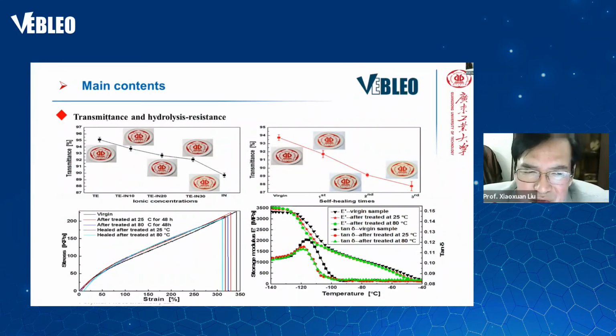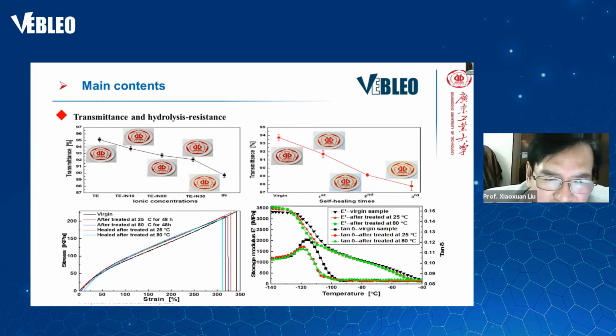Next, let me show you transparency and hydrolysis. For transparency, the silicone elastomer has very high visible light transparency, up to 90%. After heating times, it is slightly decreased, but its persistence is 88% above. And the highest transparency is up to 60%. So it has good persistent factors.